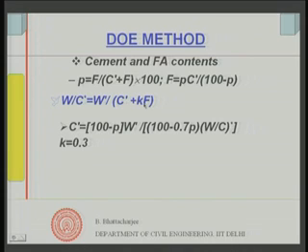So, C dash plus Kf one can take, and this is then the equivalent cement content, and W dash is the water content I have obtained after reduction. So, my equivalent water cement ratio in the case of fly ash concrete will be given by this, and this must be equal to the water cement ratio star of the control mix. So, my control mix had water cement ratio star, and this must be equal to W dash divided by C dash, where C dash is the cement in the new fly ash mix, multiplied by K plus F.